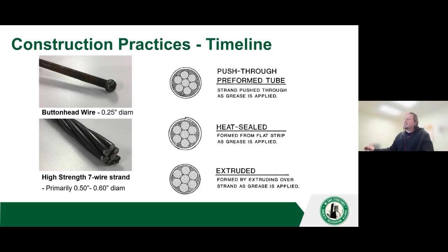Something to note with the tendons, earlier tendons that weren't buttonhead, like you see on the top left, where we're just using a 7-wire strand, either 0.5 or 0.6. There were push-through tendons, so it was a grease tendon pushed, basically through a tube or like a hose. Then there's heat sealed; those were wrapped around the tendon, and sometimes that seal would break open and cause a vulnerability in the sheathing. And then there's extruded, a tightly formed sheath wrapped around the tendon. You can see the deformations of the wire through the extrusion. Very well bonded, tight, durable. So over the years, material practices have changed. Plastics have gotten better and more durable, more flexible for these types of applications.